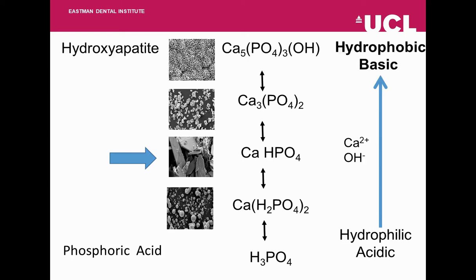To explain a little bit about remineralisation, the reactive calcium phosphate in monocalcium phosphate particles is produced upon neutralizing phosphoric acid with calcium hydroxide. Calcium and phosphate ions precipitate from acidic solutions as plate or needle-like dicalcium phosphate crystals, depicted in the figure in the slide. In neutralizing body fluids, however, the dicalcium phosphate will transform into balls of hydroxyapatite crystals with a porous honeycomb-like texture. This is what we hope to see with our material, allowing bone integration, because the bone is also very porous. The hydroxyapatite crystals have a similar calcium to phosphate ratio to bone also. Thus, the remineralization of the composite will allow better integration with bone, as well as healing the fractured site.